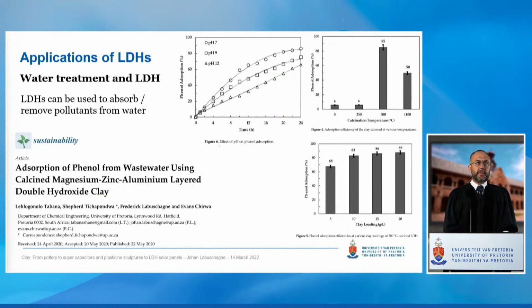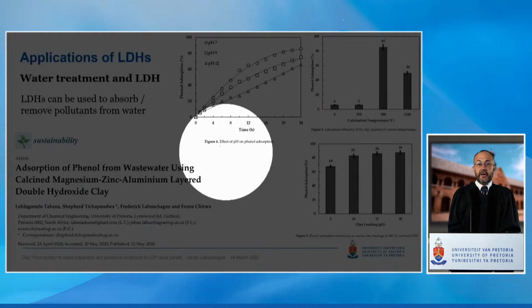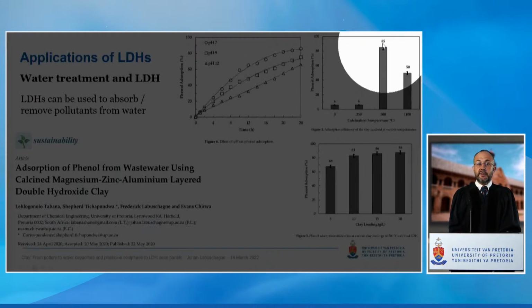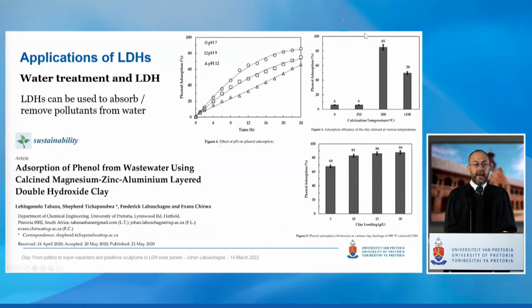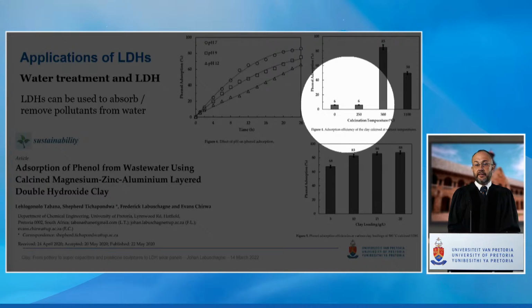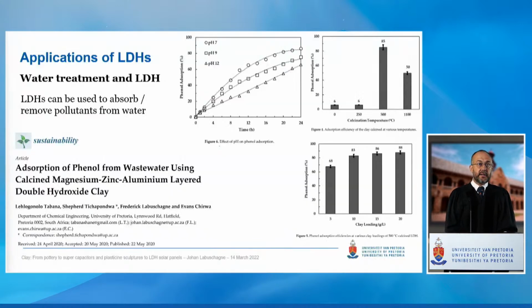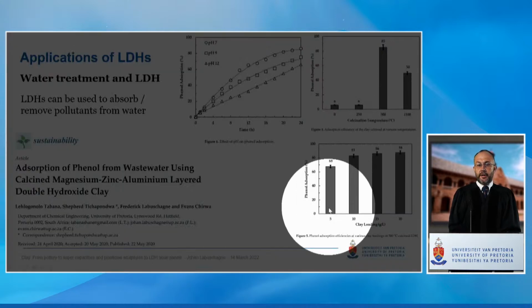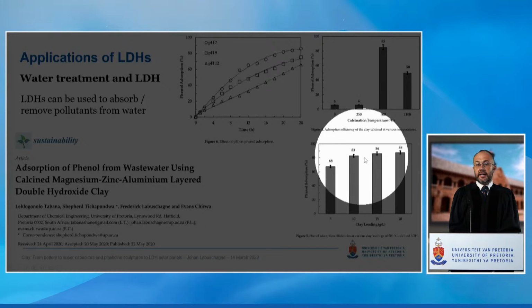Next, we also dabbled a bit into using LDH in water treatment. This specific study, done with a co-worker at the university, showed that we could get 85% phenolics recovered out of wastewater by adding LDHs. At the bottom, the temperature scale there just indicates different calcination temperatures for these LDHs to activate it for the application. We also tested to see whether loading plays an effect, and we can see that it clearly tapers off.